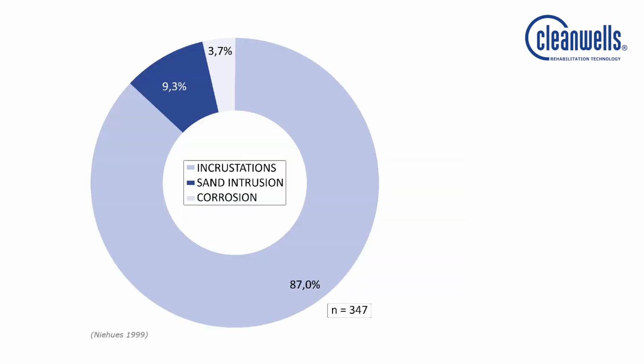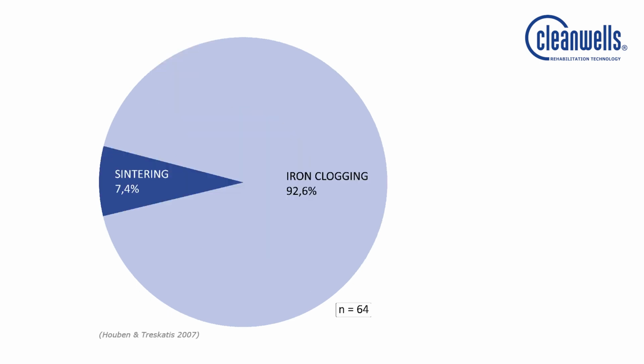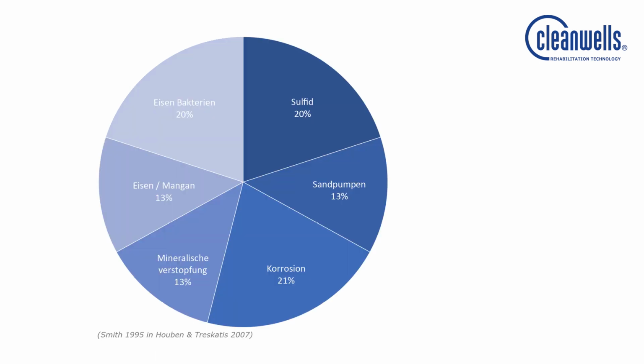In Germany, especially the growth of incrustation, with 87%, is the main reason for a well-specific decrease of yield. Iron and manganese oxides, hydroxides and oxyhydroxides are the most frequent mineral deposits, both in Germany and in the United States, as we can see here from the collected data documented by contractors. This focuses the attention on their formation as well as on their temporal and spatial growth.